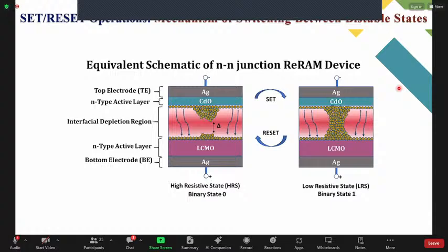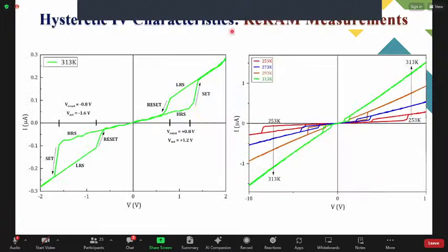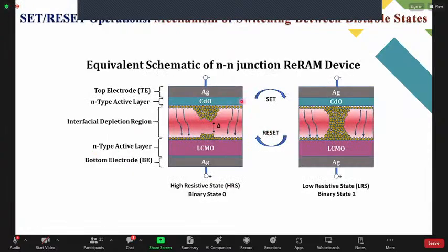Now, what is happening? Why we are getting such kind of window? So this window is showing two resistive states, lower resistive state and higher resistive state, which behave as 0 and 1. So the mechanism here is that if we apply enough voltage, so between CDO and LCMO layer, there is a depletion region. So as both the layers are N type, it is having some kind of barrier. So we have to give excess energy for that barrier.